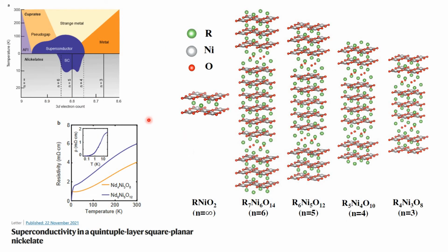So where can we find in nature something that looks like these computational experiments that we've seen? If we look at the reduced Ruddlesden-Popper series for different n values, n = 3, 4, 5, 6, we see that structurally they are formed by n nickel O2 planes, which are isolated along the z-axis by this fluorite slab, this blocking layer with fluorite structure.